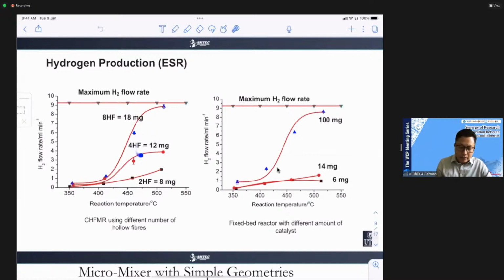If we want to make a direct comparison between our catalytic reaction inside the hollow fiber and the fixed bed reactor, we crush this hollow fiber and put it inside the packed bed. The hydrogen produced by 100 milligrams is equal to 18 milligrams of the catalyst using 8 hollow fibers. This shows that the hollow fiber has characteristics that improve the catalytic reactions.